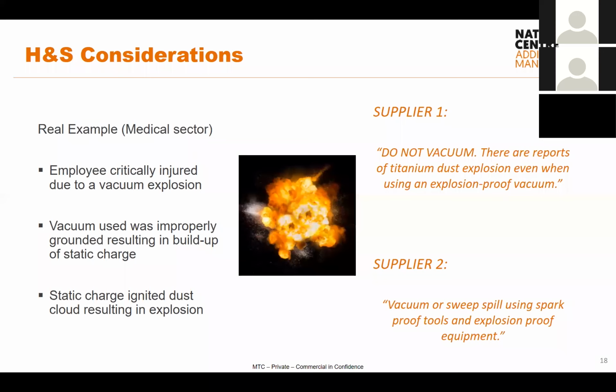But why this is such an important thing to highlight is, okay, this is clearly inappropriate. The wrong vacuum was used. But when we look at the suppliers' MSDSs, the material safety data sheets that you get from powder suppliers, we've got supplier 1: do not vacuum. There are reports of titanium dust explosion even when using an explosion-proof vacuum. Supplier 2: vacuum or sweep spill using spark-proof tools and explosion-proof equipment. So even within the supply chain, there is some level of unknown and no level of consistency. And I'm not saying I have the answer, it's merely highlighting the issue that we have to consider health and safety, what is appropriate to do and what isn't appropriate to do with our materials.